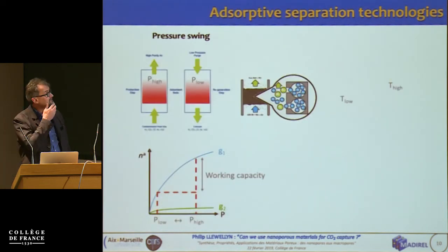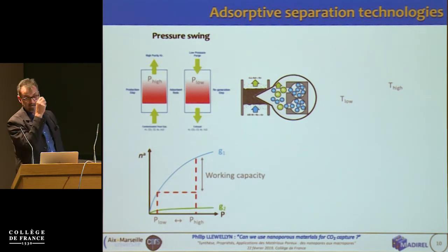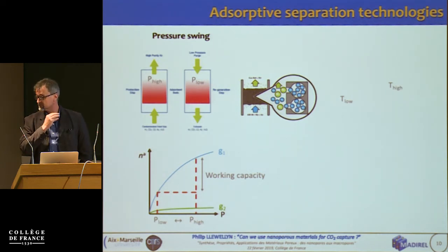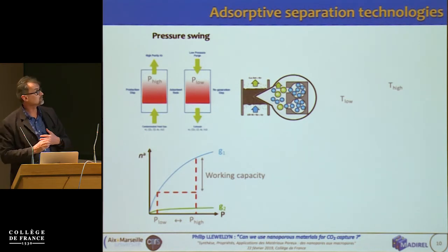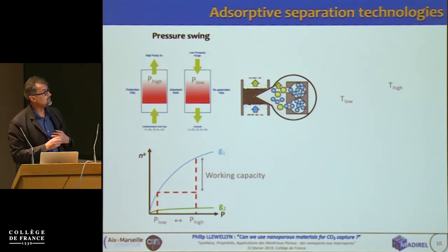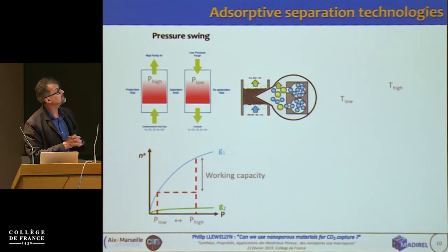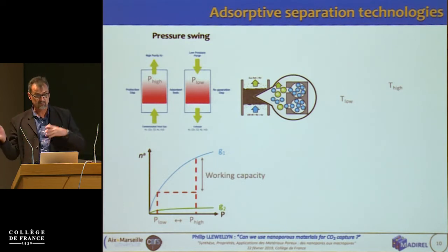Okay, so different types of technologies. One is working with pressure. We'll start at a lower working pressure, so the low end of the isotherm, go to a higher working pressure, somewhere higher in the isotherm. And what is interesting here is the working capacity, the difference in uptake between our lower working pressure and our higher working pressure. And if we have a good separation, CO2 and nitrogen, for example, we'll have a bigger working capacity for gas 1, CO2, and a much lower working capacity for gas 2, which would hopefully be our nitrogen. And basically all we do is go up in pressure and down in pressure and play around.